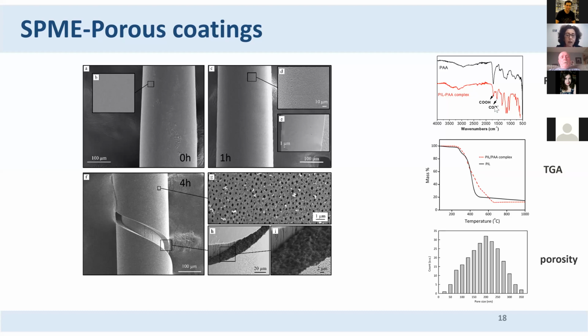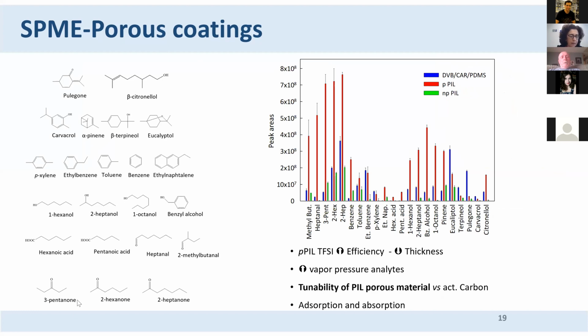So let's see how this fiber performs. So we had great hopes on this fiber. So we tested a very wide sample of compounds, and these are the results that we got. First of all, realize the difference between having a porous fiber and a non-porous fiber. So it's the red and the green. So the red, the peak areas are much higher. It has a much higher sensitivity than the green.